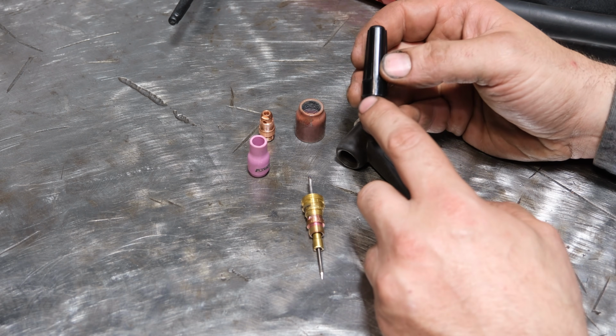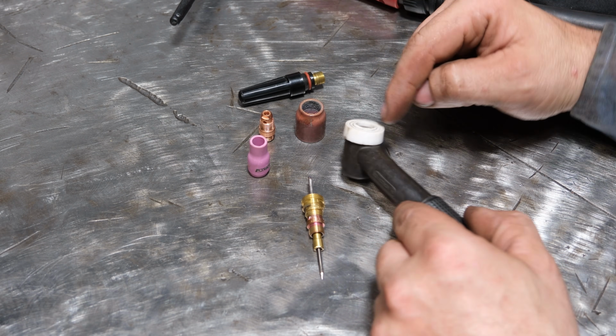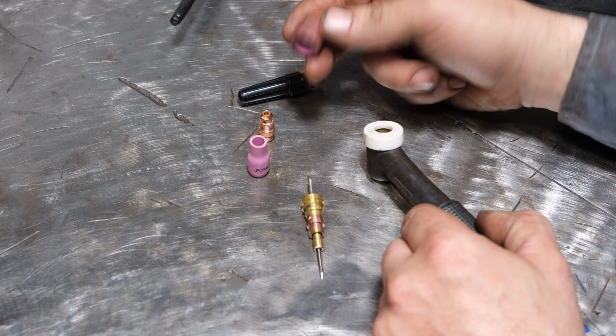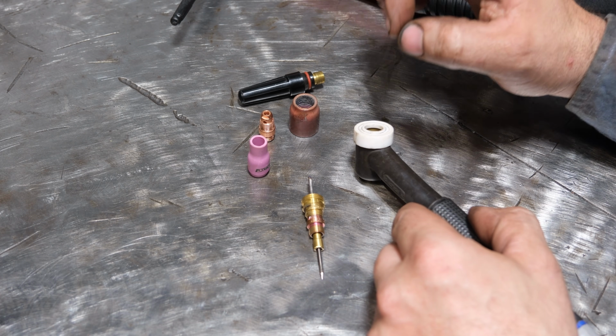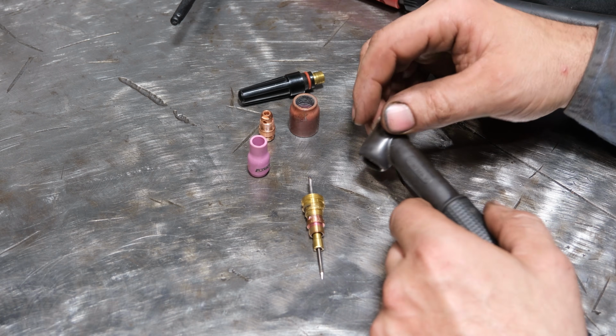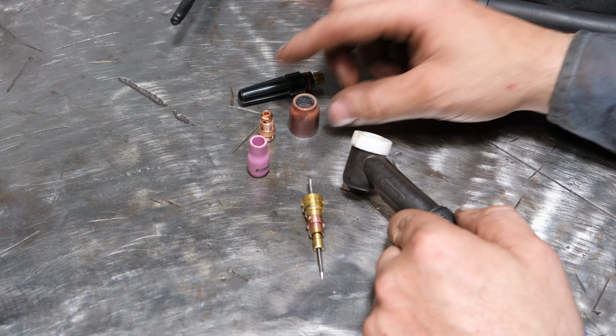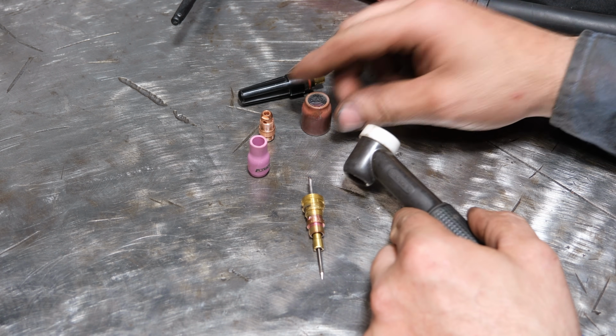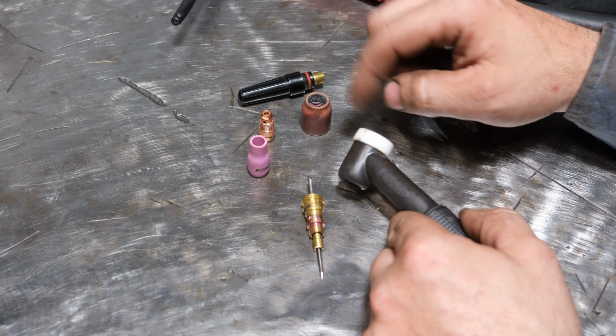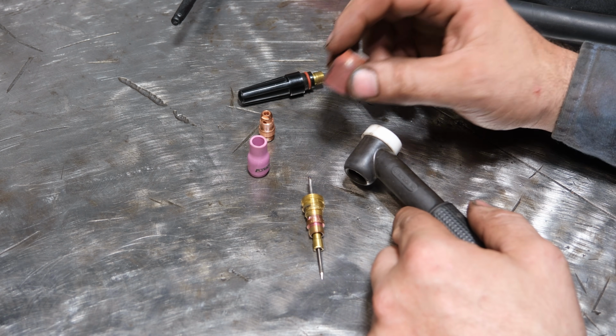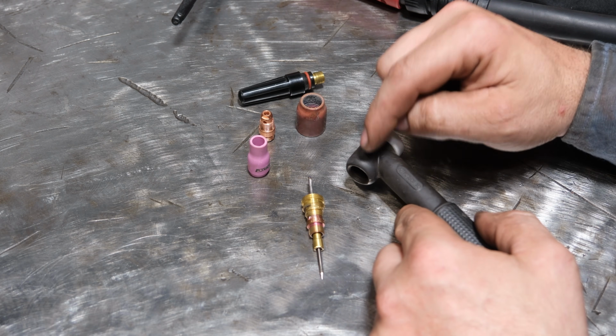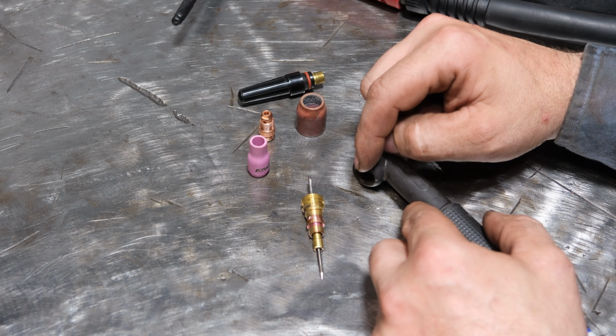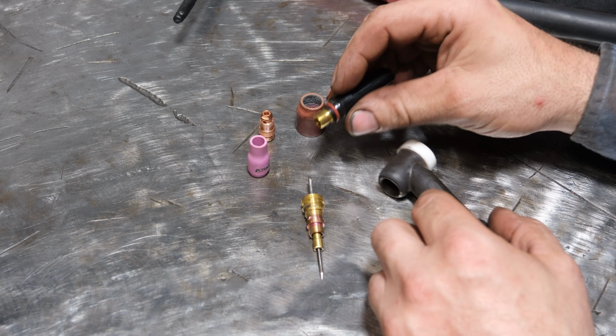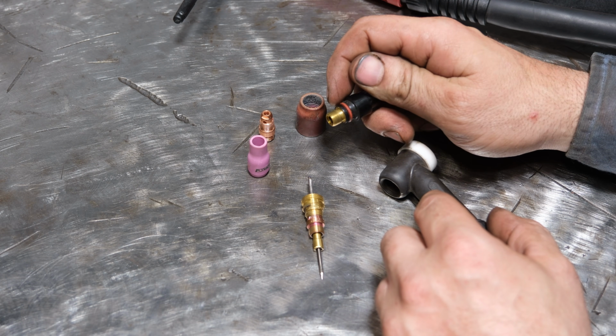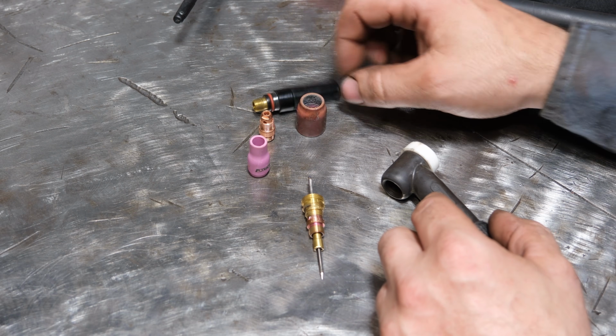By the way, there's an O-ring on this, and occasionally there's O-rings as part of this assembly with the gas lens. If those leak, you can either end up getting less argon out of your cup than you expect, or it can pull in air from the backside and contaminate your tungsten and your weld. So it's important that you keep O-rings in good shape, like this guy right here, and you replace them if they're nicked or missing, because it will cause issues.